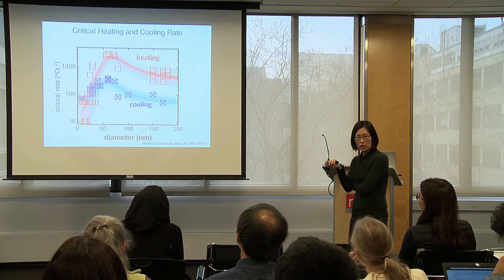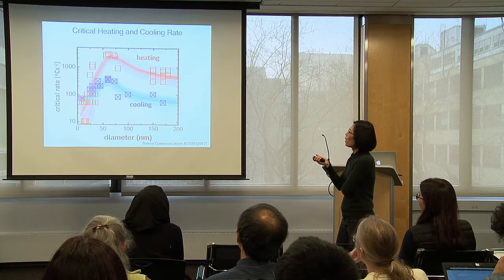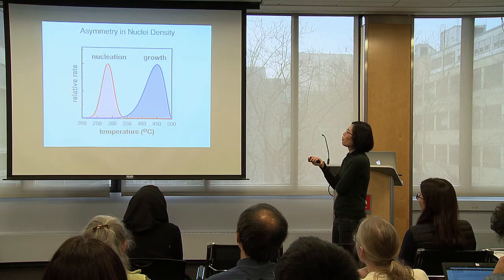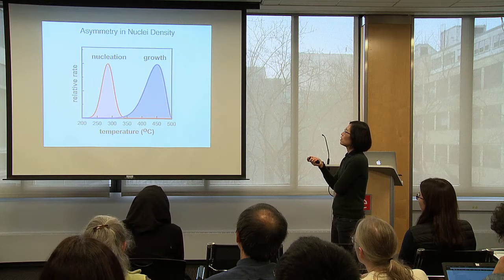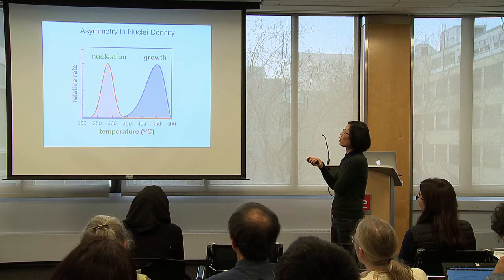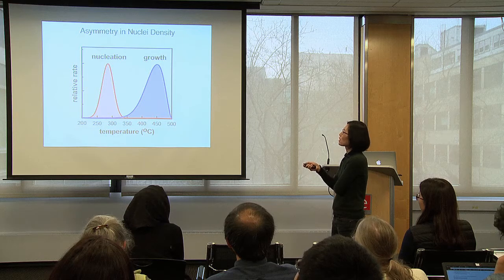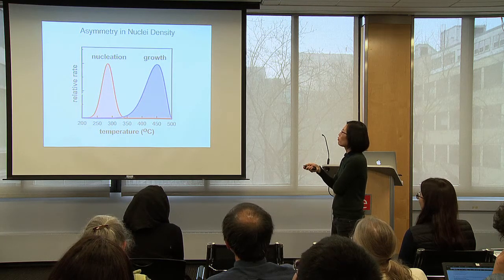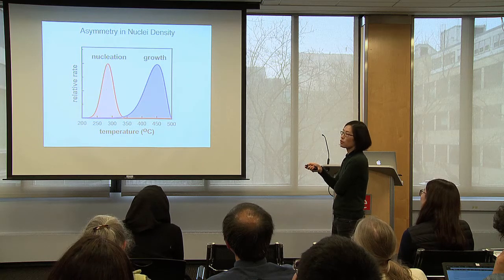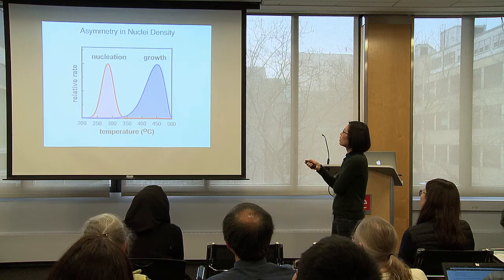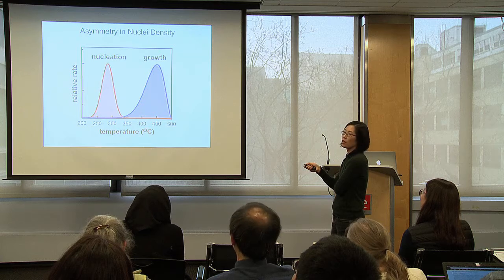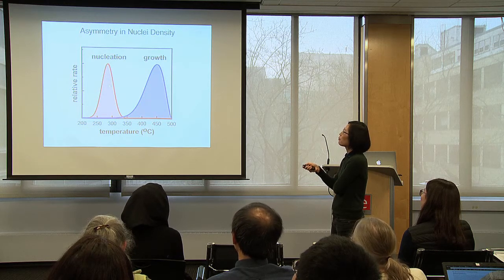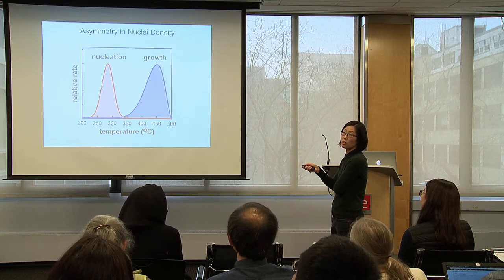That's been observed in bulk samples. And the way we explained this in the field was to recognize the fact that the temperature spot where a lot of nucleation events happen is at a lower temperature spot compared to where a lot of growth happens. So if you're heating, you first created a lot of nuclei, and then now they grow. Okay? Now if you're cooling, you're first coming down from this side, so you don't have that many nuclei. Okay? So there's nothing to really grow. And by the time you create nuclei, your growth is slowed down.